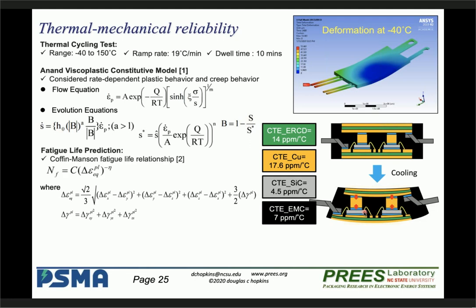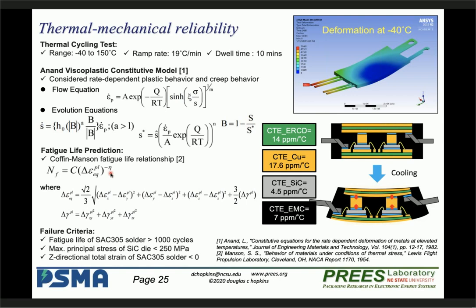Next, it's about the fatigue life prediction model. So in order to quantify the lifetime of the power module, I applied the Coffin-Manson formulation, which is commonly used in the industry. So in the equation, N_f means the fatigue life, and epsilon here means the equivalent plastic strain, and the C and eta are the constants that depend on solder material. Okay, finally, here are the criteria in the mechanical simulation that I defined. So basically, I monitor the stress and strain on the die and solder because those are common failure points.